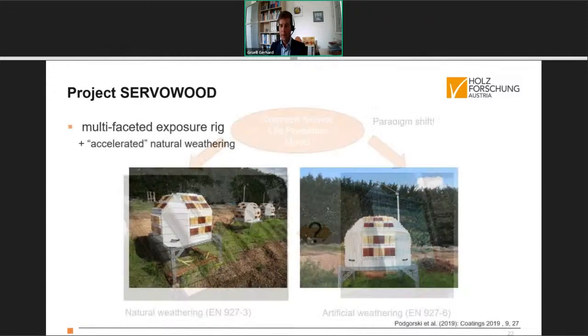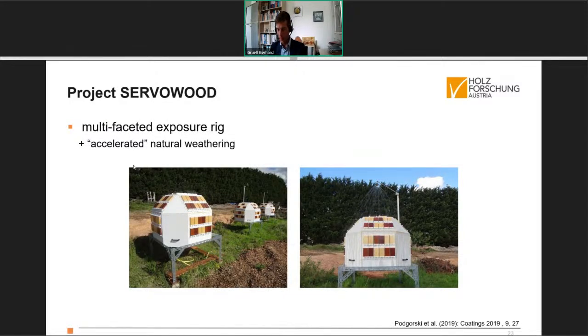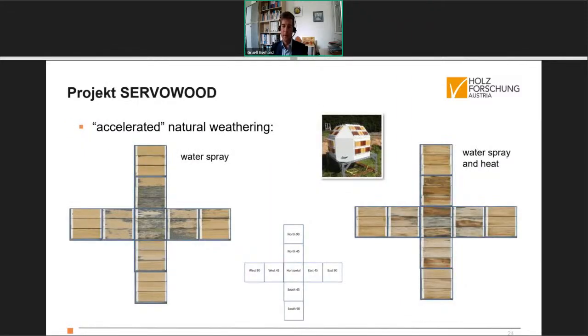There was also a very interesting natural weathering trial with special setup with these multifaceted exposure rigs, where we could expose coating systems in 9 different directions. And also some of these rigs had additional showers and heaters inside these boxes, so that we can also introduce more moisture and more heat. And this in total is a dosage variation in natural weathering, which was the approach of this trial. There is a paper from Laurence Podgorski from last year, where you can read some results on fungal growth of these surfaces.